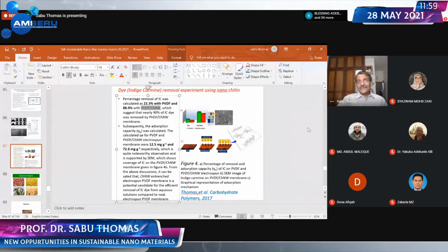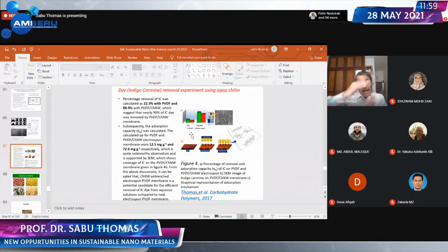And he wanted to remove indigo carmine dye from water. This is again a very important dye being used by the textile industry. If you use PVDF alone, the removal efficiency is something like 22%. But if you combine PVDF and nanochitin together, the removal efficiency becomes 88.9. So you can make wonderful filters by combining PVDF and nanochitin together.